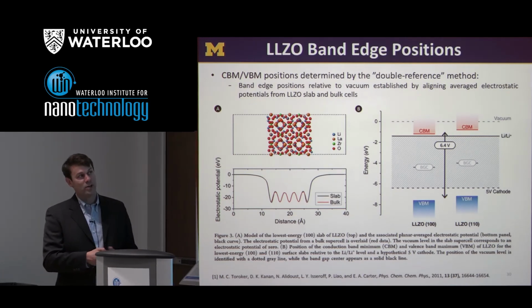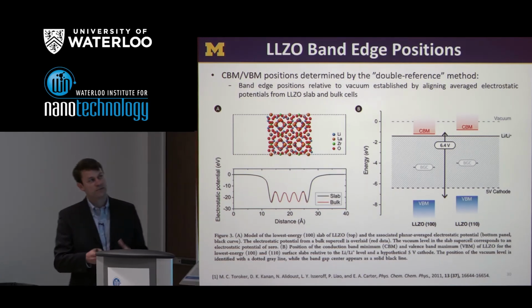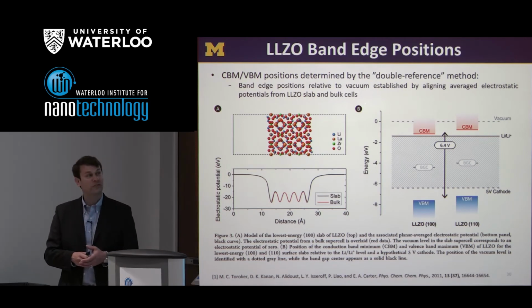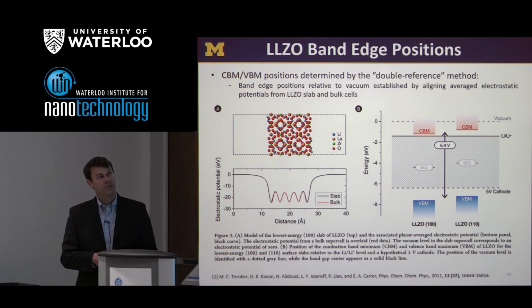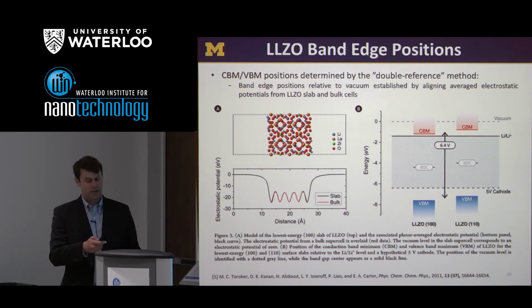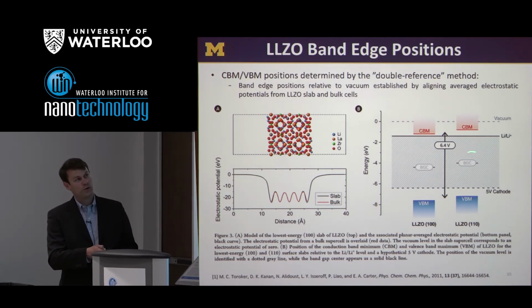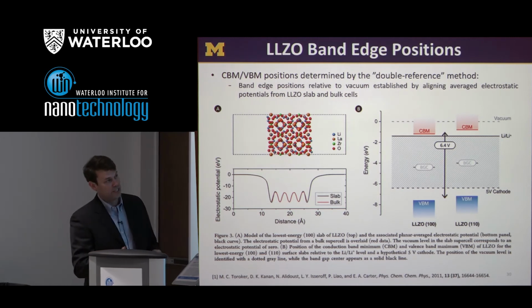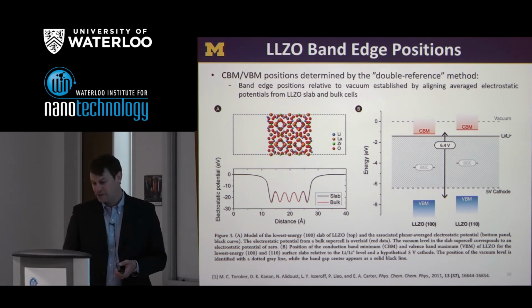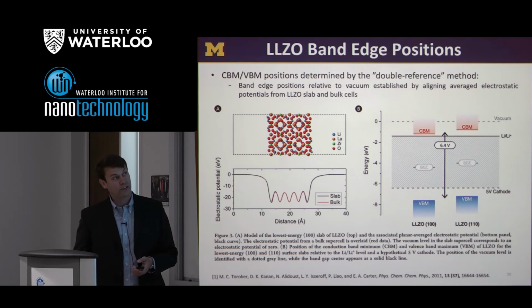It's not way above the lithium/lithium plus level, suggestive of some moderate reductive stability. But this is quite different from what we would see, say, for most liquid electrolytes, where the LUMO would be below this level. So this indicates some perhaps enhanced stability with respect to reduction of LLZO.